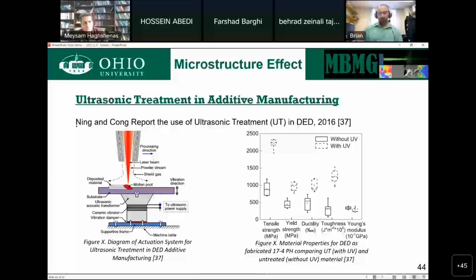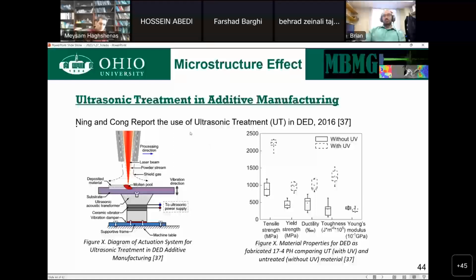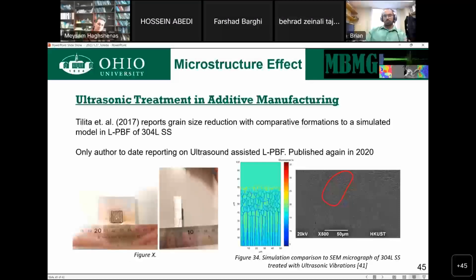So this is the premise of what we have. This is from a publication focused on direct energy deposition. We use a very similar approach, but in our case, we don't directly mount the build plate to the transducer. We just sandwich it between and mount on the sides here, and we have to add a gasket so that the powder does not come down through the sides. And what they found was that with UV, there's an increase in things like tensile strength, yield strength, ductility, toughness, all the things we want.